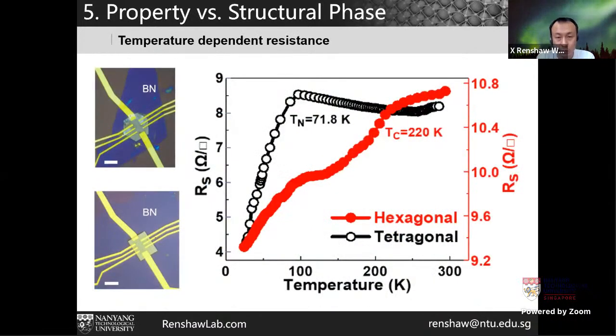This is the transport property measurement. The y-axis you can consider as a resistance, or sheet resistance. Horizontally, it's temperature. For the black curve, which is the tetragonal phase, resistance goes up, and then at around 70-something K it goes down. By checking the turning point, that is the magnetic influence on the resistance. Of course, if you check the literature, you can clearly see it is the Néel temperature for the antiferromagnetic phase.